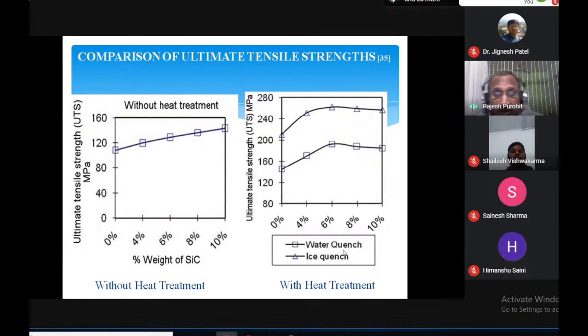And these figures are showing the comparison of the ultimate tensile strength with volume percent or weight percent of the SiC particles. SiC particles are used. The first, left figure is showing the variation of the UTS with the weight percent of silicon carbide without heat treatment. So you see without heat treatment we get quite lesser tensile strength as compared to the right one, where heat treatment has been done.